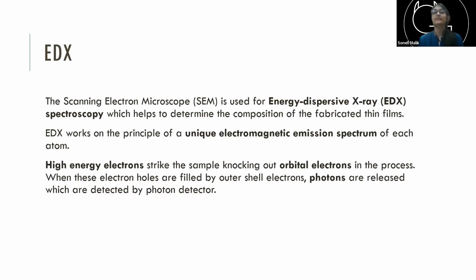Okay, so energy dispersive X-ray spectroscopy. In this case, a scanning electron microscope has an electron source that hits whatever material you want to study with really high energy. These high energy electrons knock out the orbital electrons of whatever materials are inside. And when these electrons have been knocked out, they create holes.